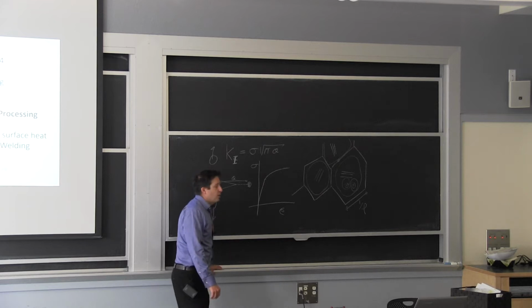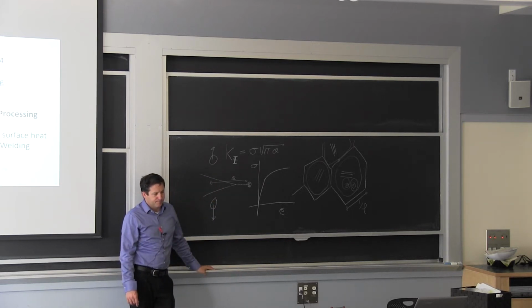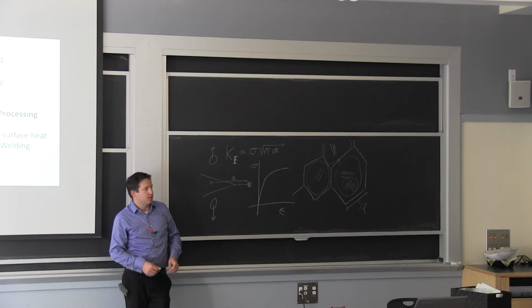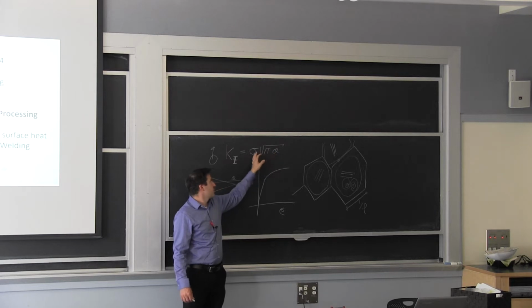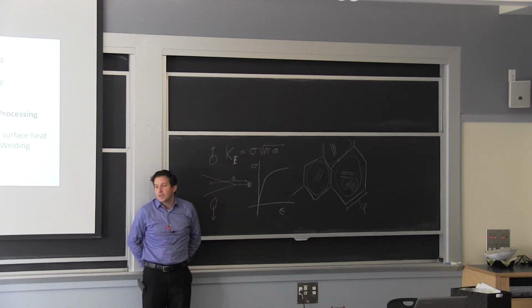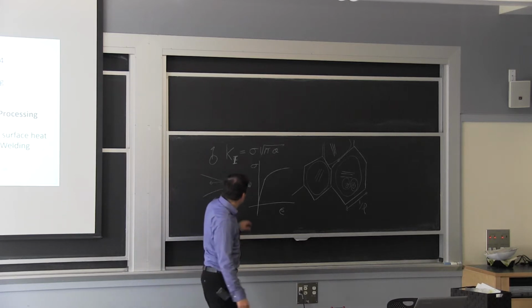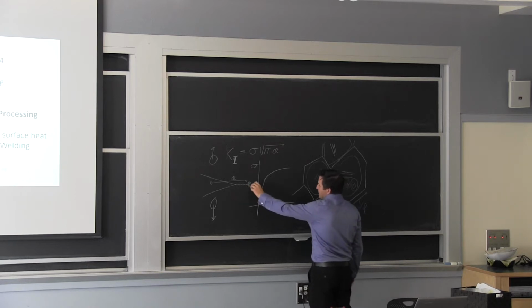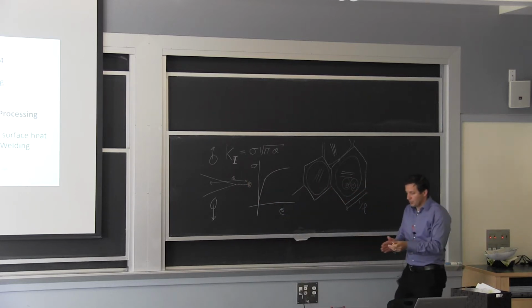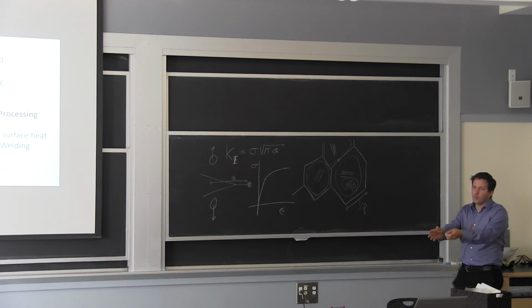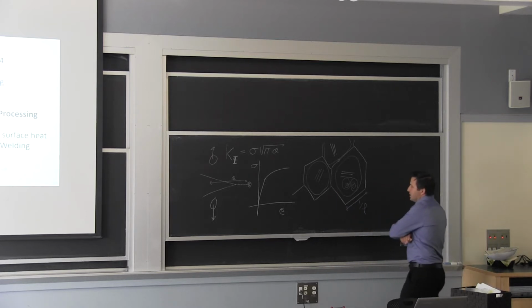We actually use this concept for large cracks. The project I mentioned a little bit about the transmission towers that are coming down, they have cracks that are inches long. And that's a situation where it's big enough that this is a kind of stress they can get from wind loads, and therefore the crack continues to grow. And it continues to grow because you have that plasticity here, so wind comes in, you stretch the crack. Wind goes the other way, you reclose the crack, and as you do this, you're just opening it. Opening and closing, and you're moving forward. So you tear one time, you close, you tear again, you close. And that's why we have a lot of times these fatigue striations for each cycle of loading. And they all involve a lot of plasticity that relates to those grains here.